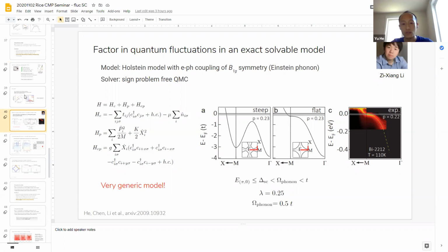Right. So what we found really interesting, I'm glad you brought up the iron selenide, iron tellurium selenium example. For those in the audience who are not as familiar with this system, it has a very, very shallow gamma hole pocket in the electronic structure, where the hole pocket Fermi energy is comparable to or even smaller than the superconducting gap size. And those are the systems where people suggested there can be a solid state BEC limit.